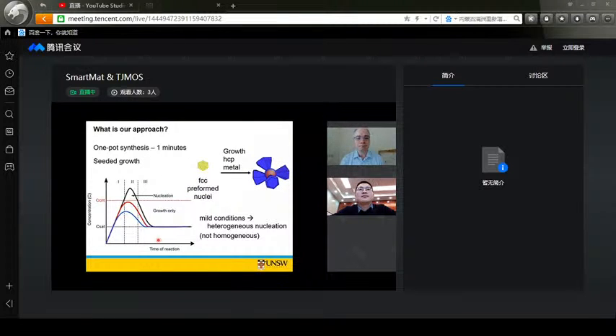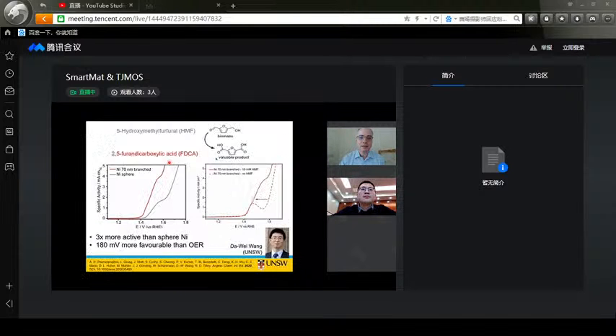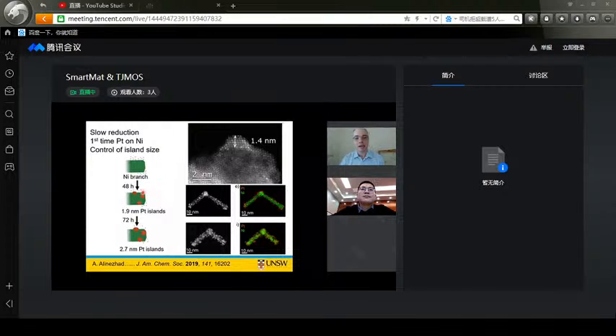And the other key point, as I said, is really for us anyway, these very, very slow times. You can do these one-pot syntheses in the space of a minute. But as I showed with our decorating, to grow these very, very small platinum islands on our nickel, it actually took 2 days. You could put your reaction on, stop it after a day, look in the microscope and think you haven't got anything. So you do need these very slow processes. The slower the better, really, if you're after a thermodynamic product, and if you're really after a coated product where you're getting the heterogeneous growth.